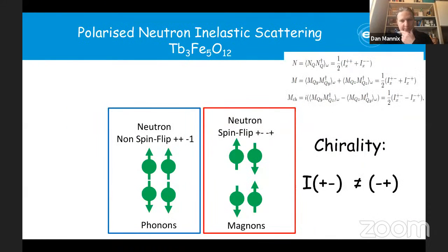So we've used magnetic inelastic neutron scattering, and I'll go very quickly here. There are two types in these polarized inelastic neutron scattering methods of interest. One is that you have a spin up neutron that is scattered with the same polarization, spin up. These are called the non-spin flip channels, so you have up, up, or down, down. This still gives you information on atomic excitations like phonons. The magnon excitations come from spin flip channels, so this is up being flipped down and down being flipped up.